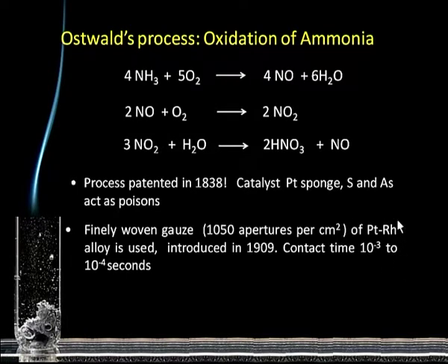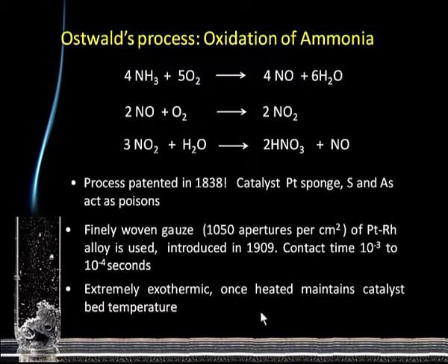A platinum rhodium alloy is used with about 10% rhodium in it, and this reaction is exothermic, and therefore once heated it can be self-sustaining. The contact time being very low, we are using a wire mesh, and that has to be supported on a ceramic support for success.